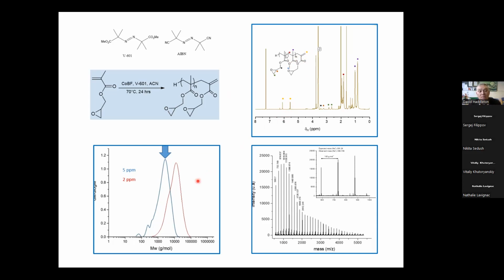We change the amounts of cobalt, and we'll change the molecular weight. So notice these molecular weights are pretty small. So the blue one with 5 ppm is about 1,000, 1,100 Mn.